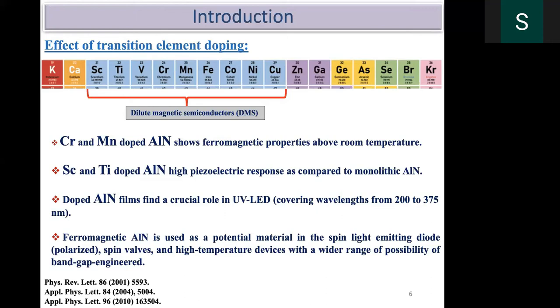Particularly this aluminum nitride is not a new material. When you dope with transition elements that you can see from the periodic table, these transition elements are very good elements which can be doped. Particularly if I say elements having electrons 1 to 10 present in the d orbitals, that's why they are called d block elements, they are very useful. The penultimate energy level and in the outermost s orbital, that is 1 to 2, are basically called d block elements. Those elements are very useful if you dope these aluminum nitride. You can convert that into a ferromagnetic material, above room temperature, particularly above the Curie temperature. And this particular thing is chromium, manganese. I will show you the magnetic moments, how much they can impart on the aluminum nitride, in the next slide.